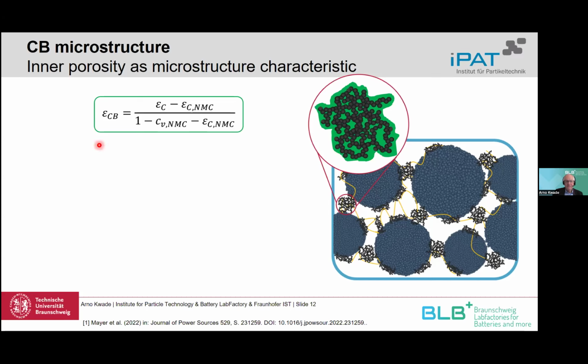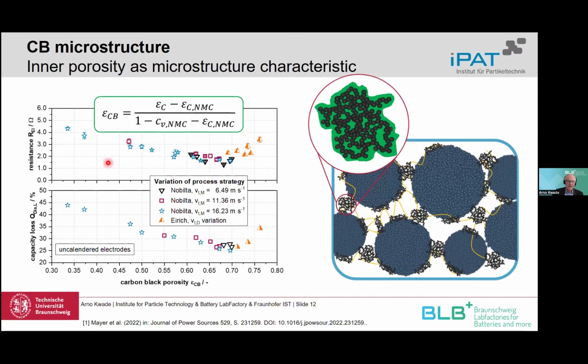And we could calculate this inner carbon black porosity using normal mercury intrusion measurements. And we could also show that the ionic resistance really depends, as you can see here, on this carbon black porosity. And there's a minimum in resistance, which means an optimum at a certain carbon black inner porosity. And you see the same here for the capacity loss of the cell at different C rates. So I think it was from almost 0.1 C up to 3 C. 3 C means that you load your cell 3 times an hour. And if you have 0.1 C, then it takes 10 hours to charge the cell. So if you have fast charging, then it gets important that the conductivity is in the right order.